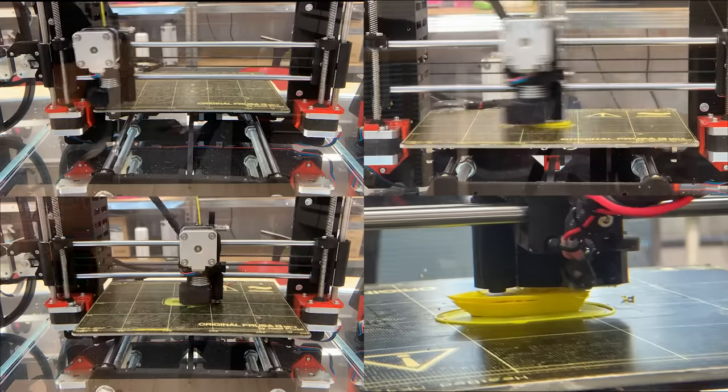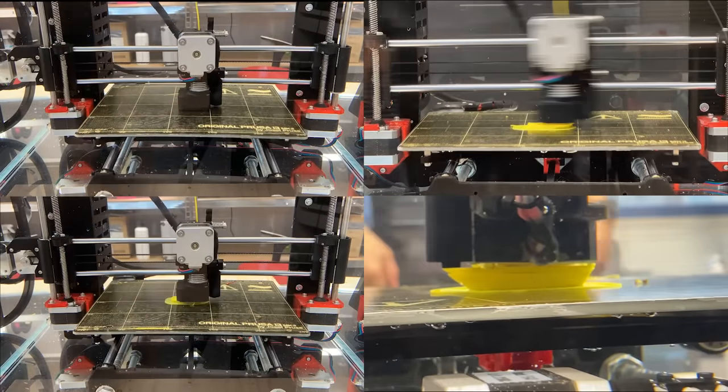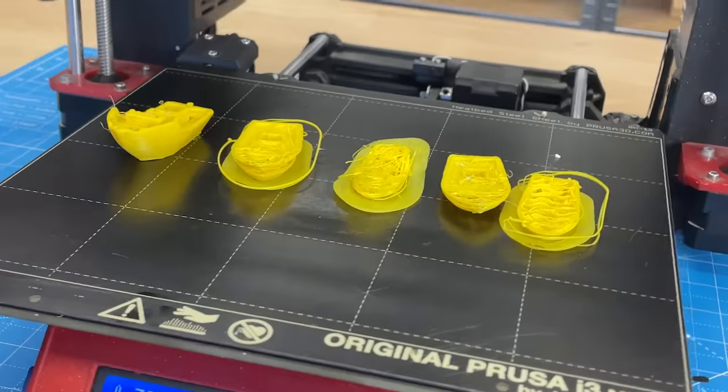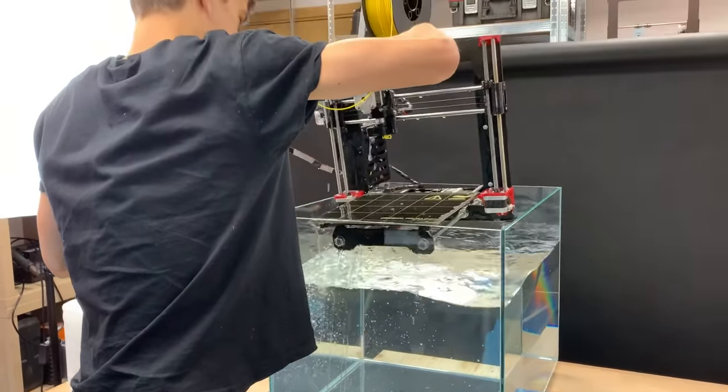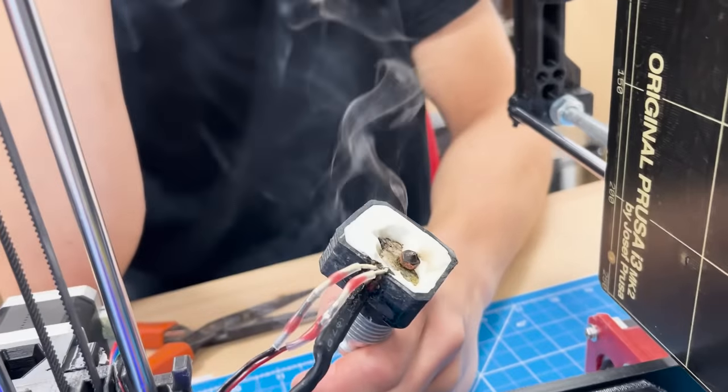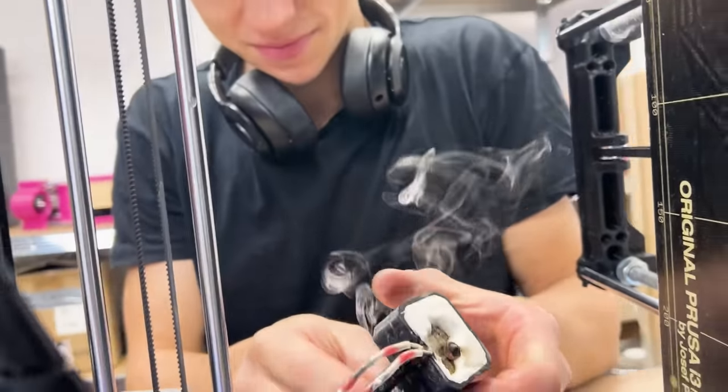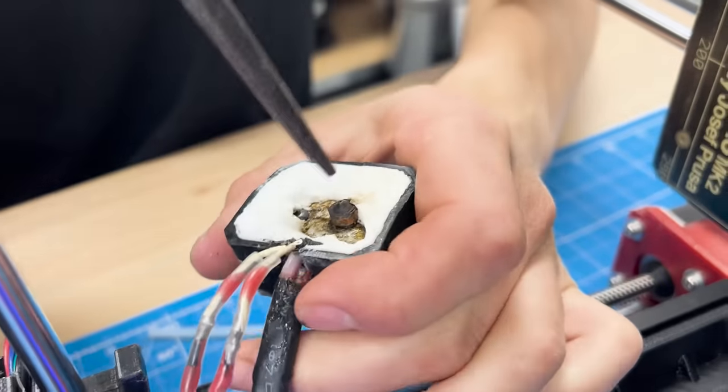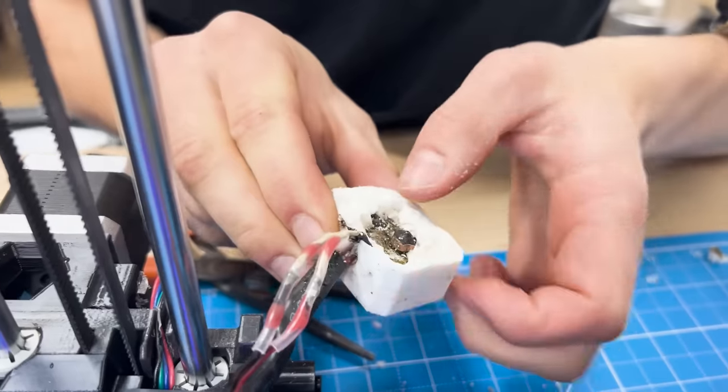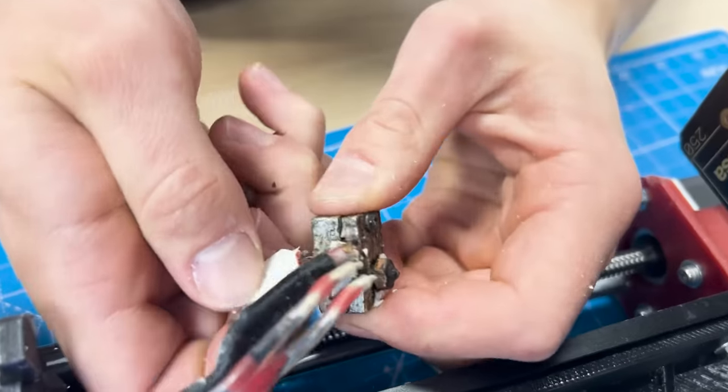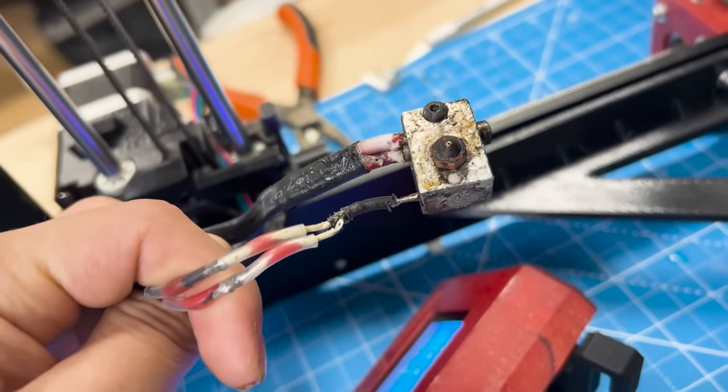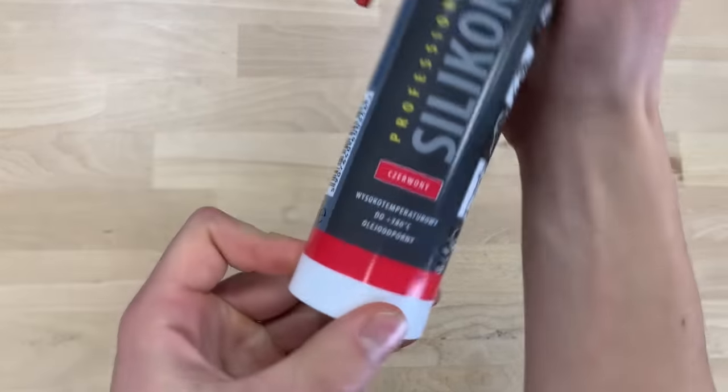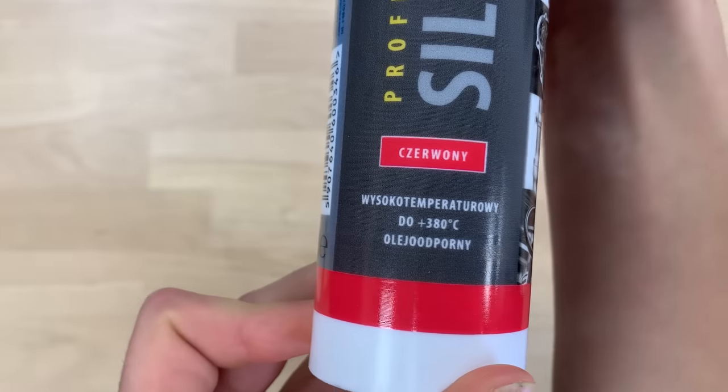However, when we tried printing the Benchy all over again multiple times, we couldn't possibly get it to work again. It seemed as if the layers did not want to stick to each other anymore. We realized what happened. The silicone insulating the heat block just wasn't made for such high temperatures. Yeah, it's like our life expectancy decreased by about 10 years this week. The water got under the silicone insulation and cooled the extruder to the point that the heater didn't even have a chance to heat it up. Let's get the printer to work again with this new high temperature rated red silicone inside the nozzle bath.